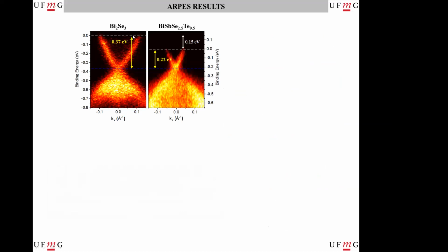The ARPES results start with two samples that we put on the ARPES. We have the bismuth selenide, and we have the quaternary sample with the four elements. And we can see here that for bismuth selenide, the distance from the Fermi level to the Dirac point is 0.37 electron volts, and on the quaternary sample it is 0.22 electron volts, which means that the addition of antimony and tellurium to the sample creates a p-type doping, a positive doping of 0.15 electron volts relative to bismuth selenide.